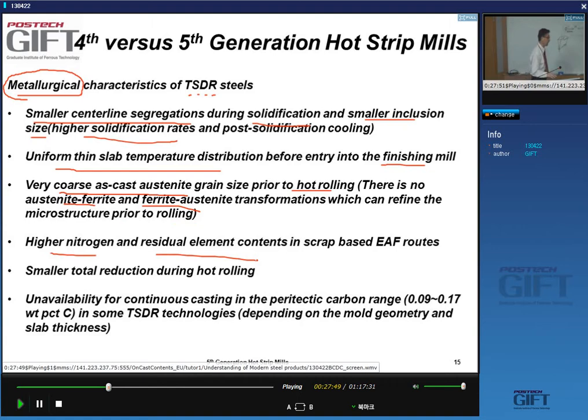Higher nitrogen and residual elements, certainly if the steel you're getting is from electric arc furnace, yes, you will easily have more than double the amount of nitrogen in your steels. That has an impact on the kind of precipitates that are formed in your material. For instance, if you're trying to make HSLA steel, which contains niobium, these very high levels of nitrogen will impact the precipitation of the niobium, and it leads to difficulties in obtaining good HSLA steels. And we have, of course, residual elements any time you use scrap-based material.